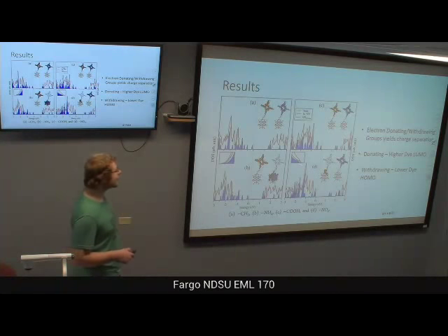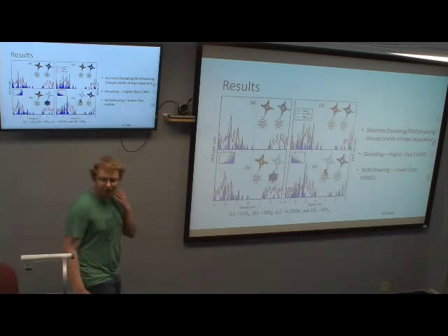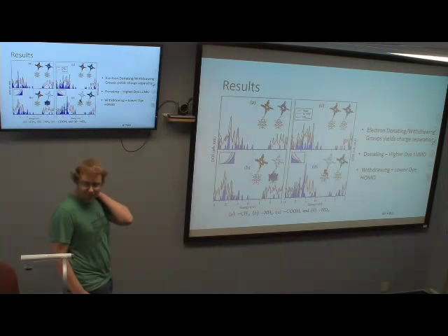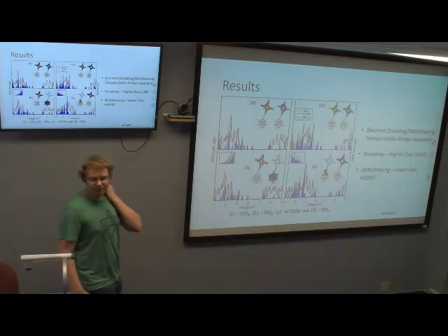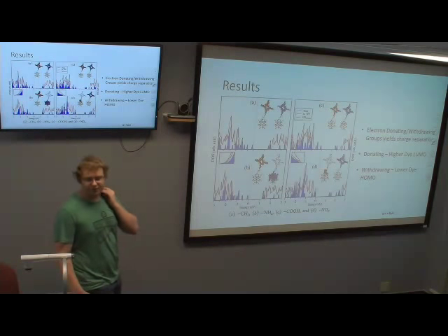The weak ones did not cause a charge separation, but the strong ones did, and these are just close-ups of this particular case. It doesn't matter whether it's electron withdrawing or electron donating, but if they are strong, they both push the unoccupied levels of the dye so the gap changes.